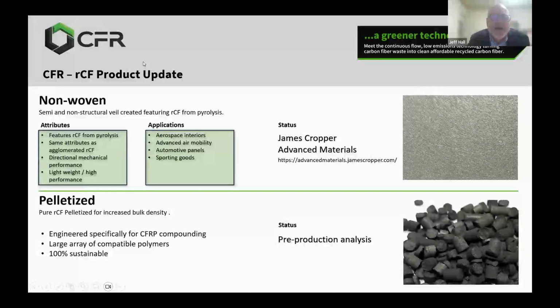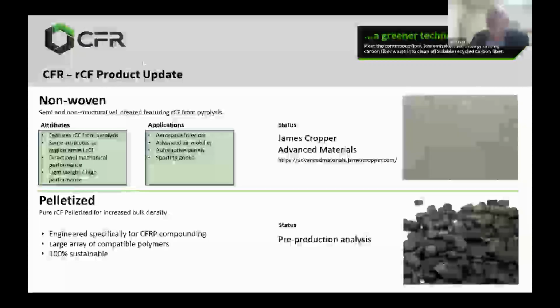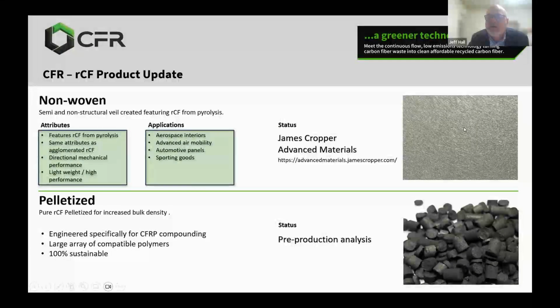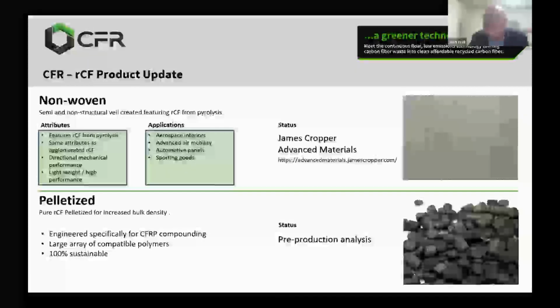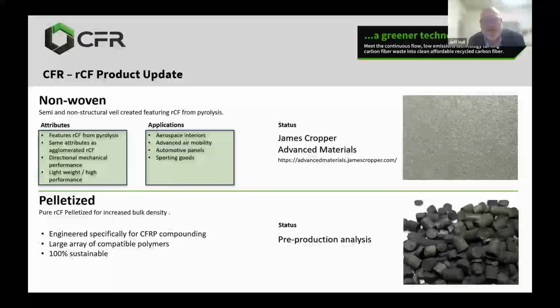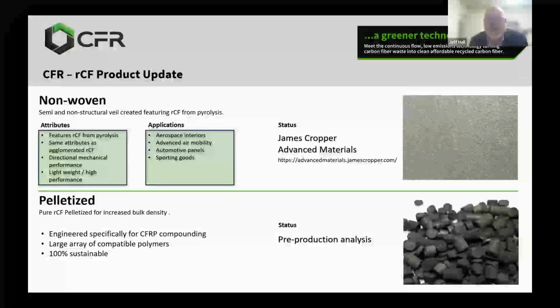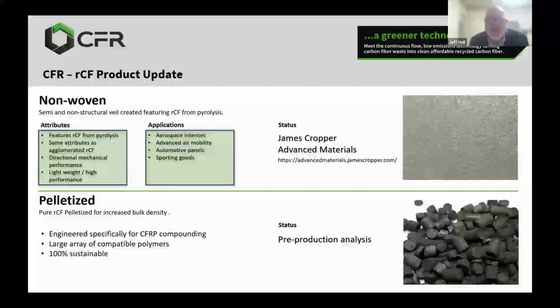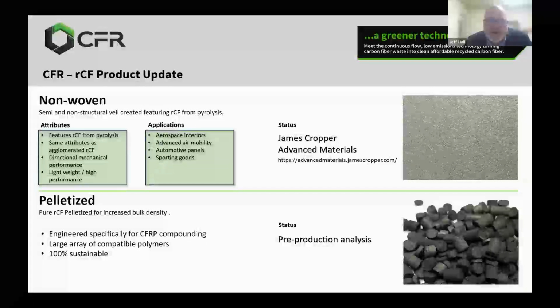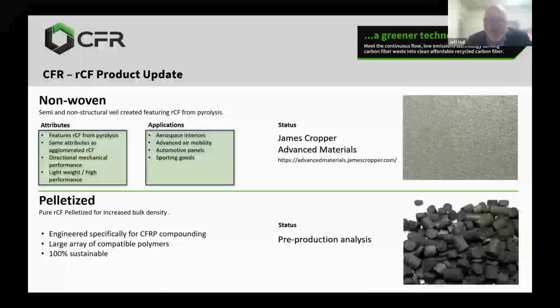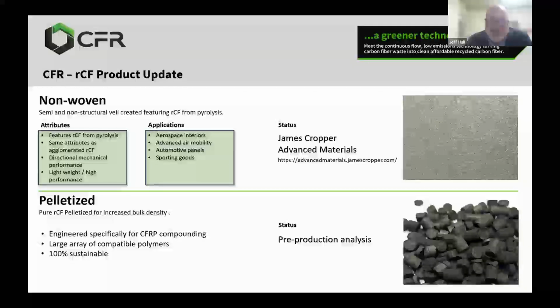And then lastly, from a product development perspective, we're also very excited to talk about our pelletized RCF. So we've taken our standard agglomerated fiber and we've pelletized it primarily for the purpose of increasing the bulk density of the material. We engineered this pelletized carbon fiber specifically for compounding, right? If you've ever tried to compound with short chop lengths of virgin carbon fiber, you'll find that the bulk density is so low that it can cause flowability issues. By increasing the bulk density of the material, we've taken that challenge away.